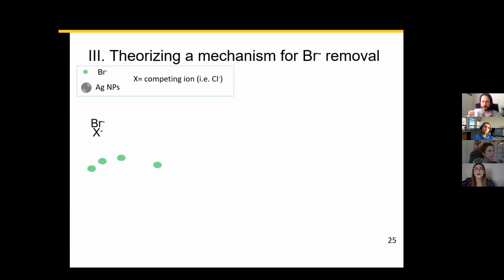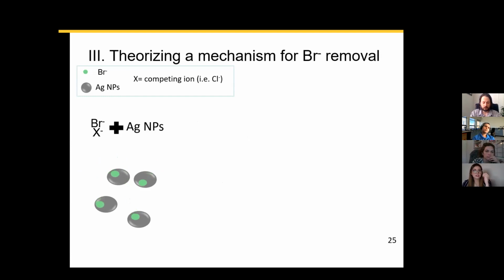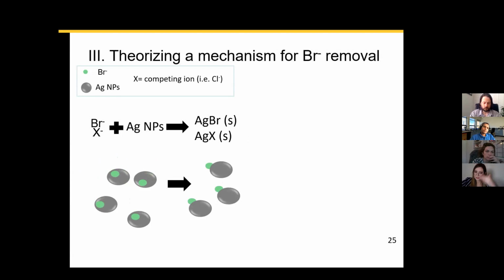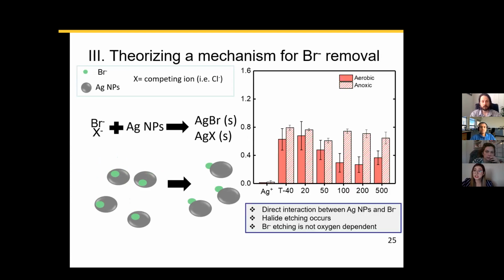However, we have another mechanism that can come into play. Let's again suppose we have this bromide ion in water that will then come in contact upon the addition of silver nanoparticles. But then we suspect a direct interaction between these bromide ions and the silver nanoparticle surface, again forming the silver bromide precipitates. In order for us to test these, we needed to do this set of anoxic experiments just to remove that dissolution effect and make sure that